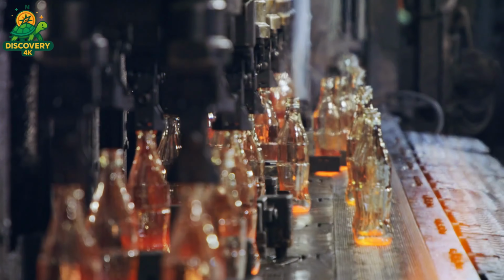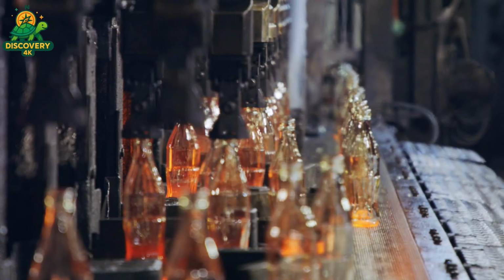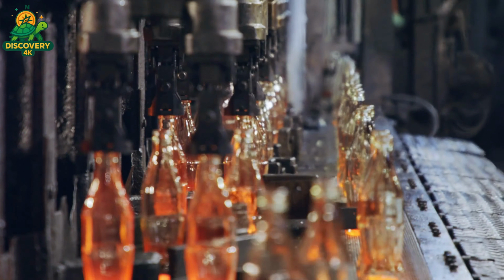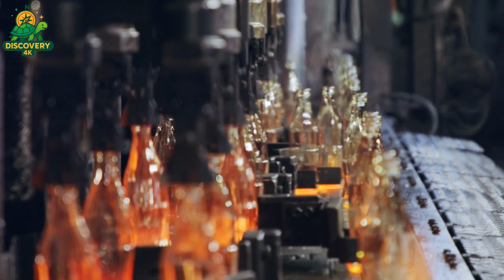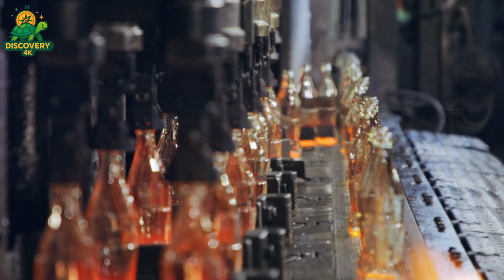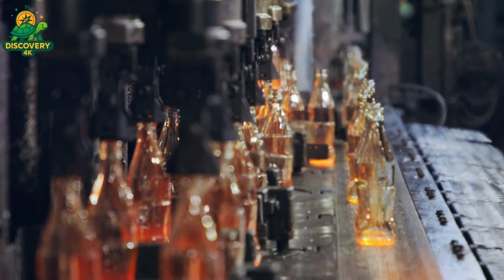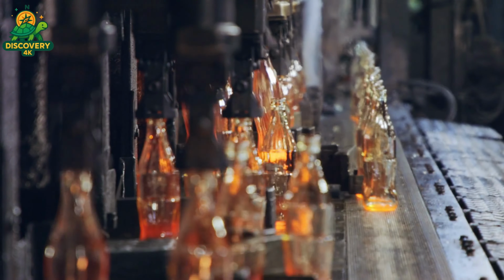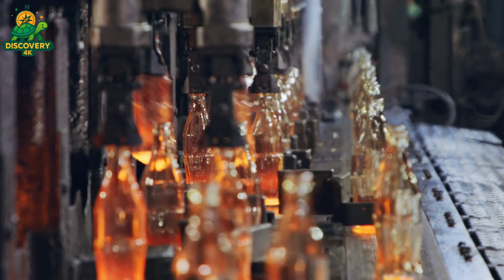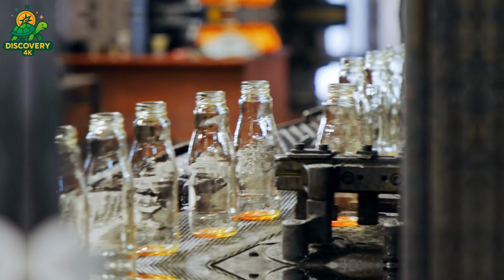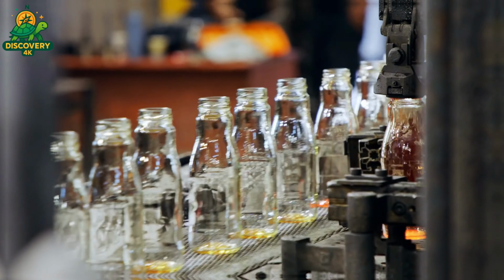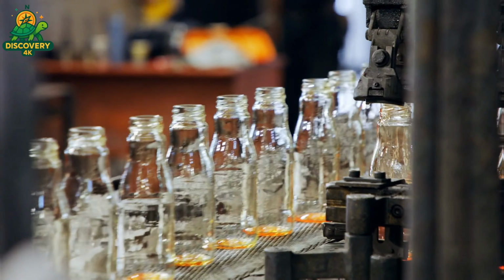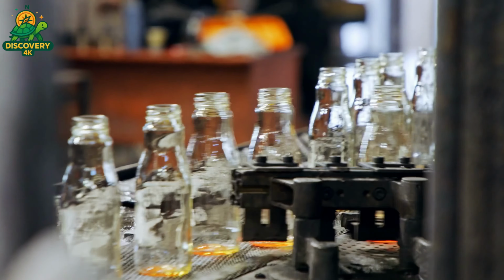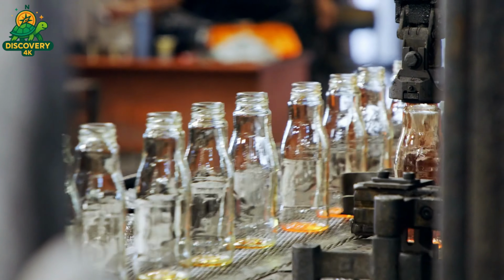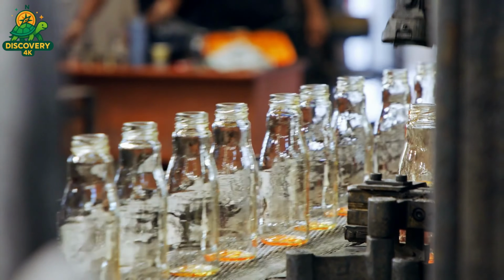Step 4. Preliminary cooling. Once the bottle is fully formed, it's cooled with a blast of air to solidify its shape. But at this point, the glass is still hot, too hot to touch, and highly stressed internally. If cooled too quickly, it would crack or explode. Instead, the bottles are gently carried out of the molding section by conveyor belts, glowing red-orange and heading straight for a long, narrow oven. This leads to the next critical phase, annealing.